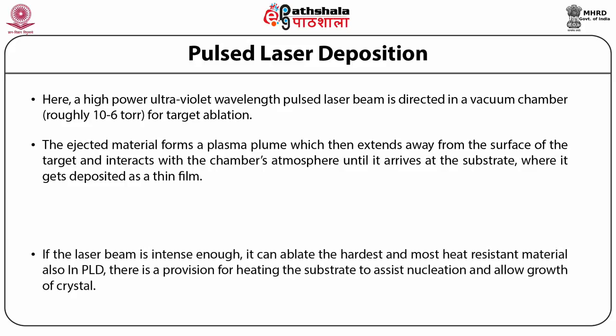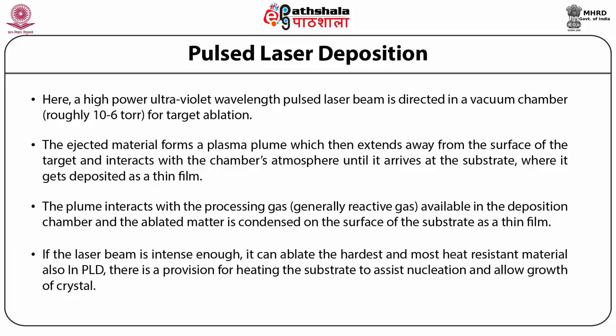So, a laser beam of sufficient energy is focused on a target. The target material goes into the vapor state directly without melting. The vaporized species in front of the target are seen as glowing plasma, called the plume. The plume interacts with the processing gases, generally the reactive gases available in the deposition chamber, and the ablated matter is condensed on the surface of the substrate as a thin film. So, if the laser beam is intense enough, it can ablate even the hardest and most heat resistant material.